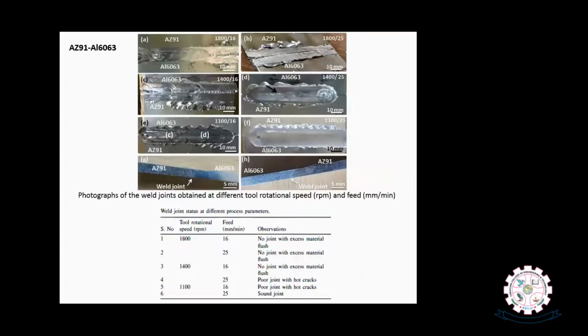Another magnesium and aluminum dissimilar joint was also performed by friction stir welding. Here you can see AZ91 magnesium alloy with the 6063 aluminum alloy. A number of processing parameters have been adopted to develop a sound joint without defects, and after carrying out a number of experiments, we have obtained an optimum set of process parameters at 1100 RPM with 25 mm per minute.